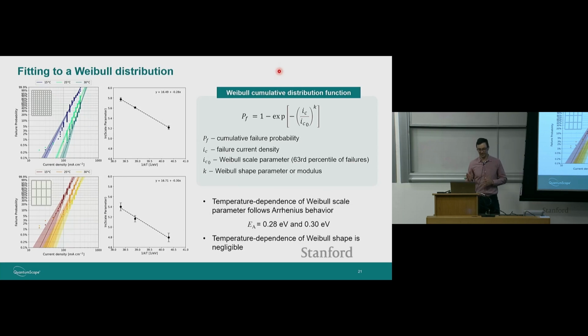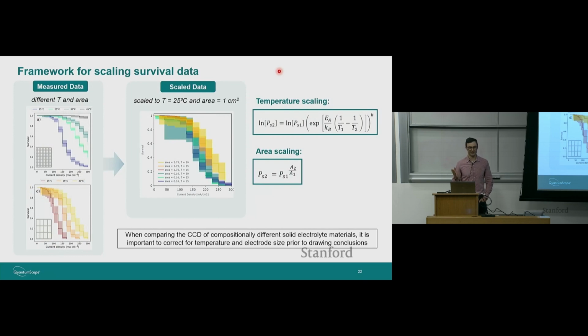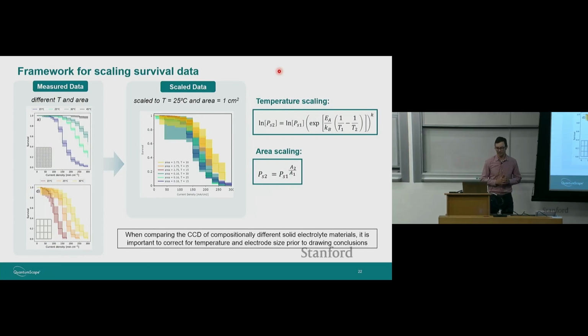So when you fit your failure population to a Weibull distribution, you can then extract a lot of interesting features from it. So it allows us to then scale our survival data with area and with temperature, as I just mentioned. It turns out if you measure and extract the survival curves, fit them to Weibull distributions over different electrode areas and different temperatures, there are good scaling laws that come out of that.